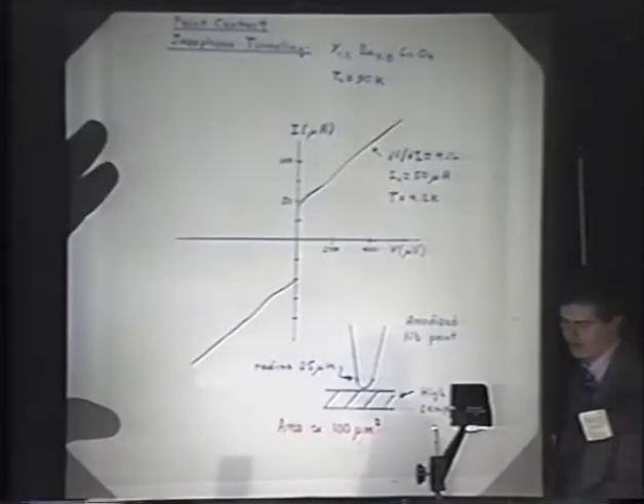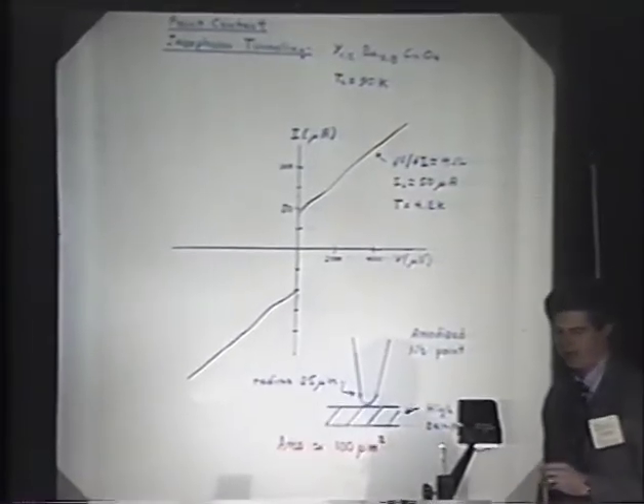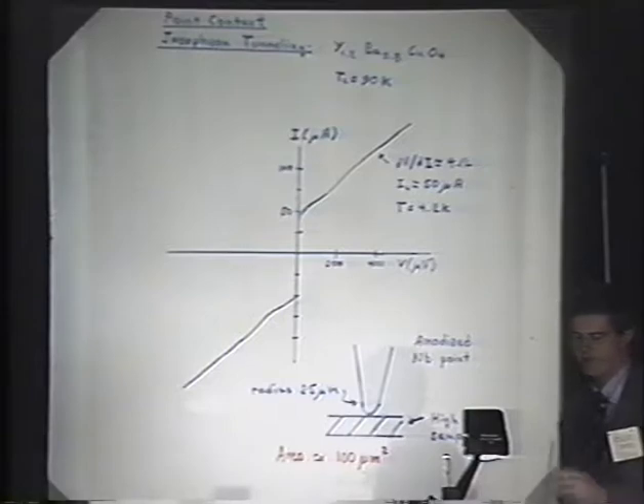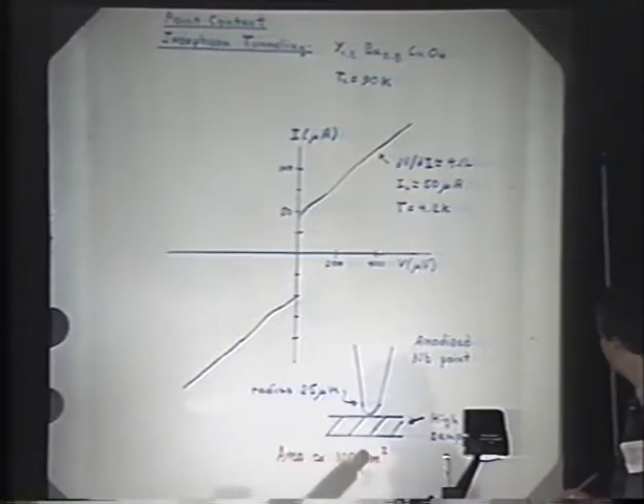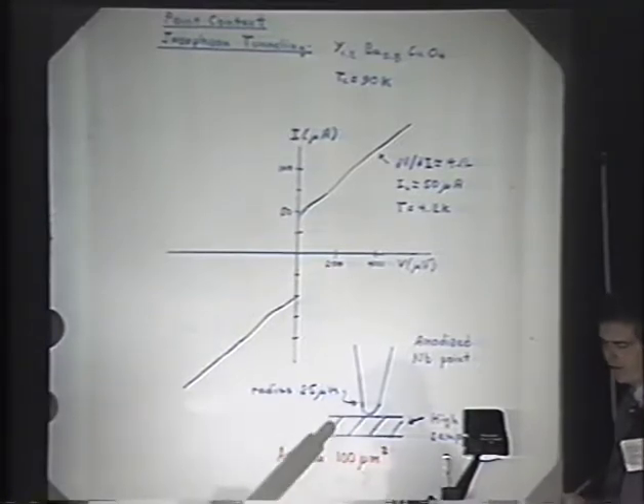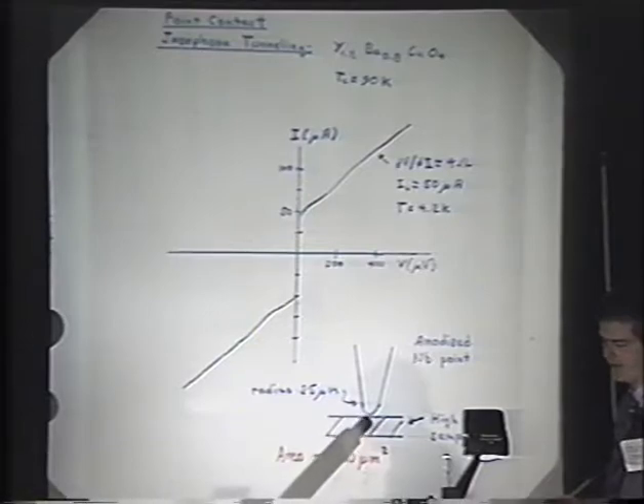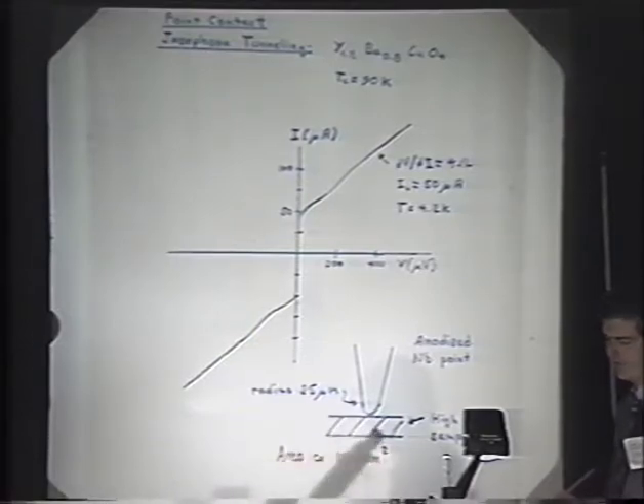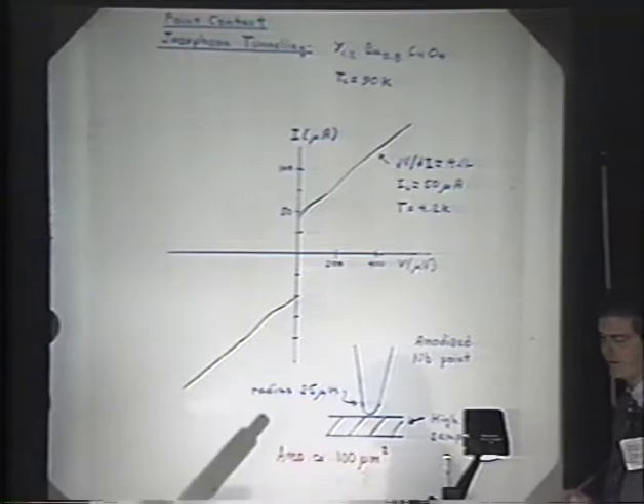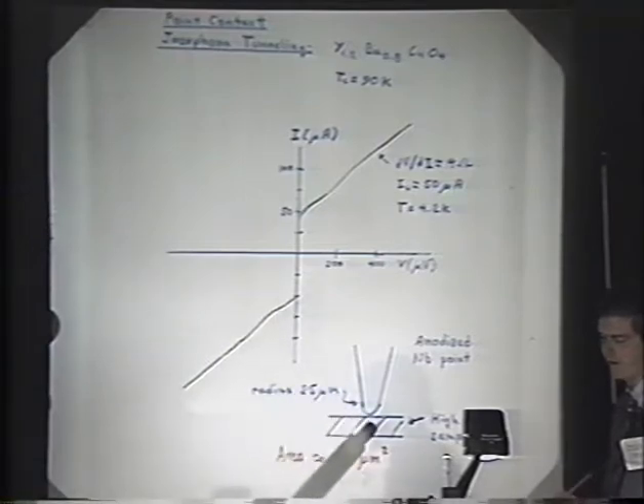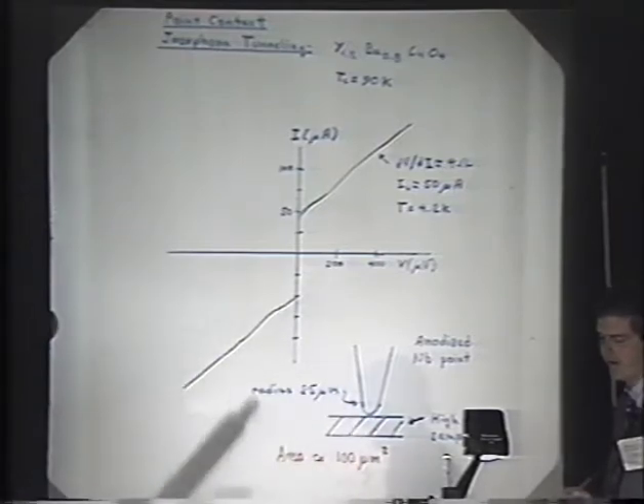Finally, I want to show you a point contact Josephson tunneling experiment. We made a point contact junction, as shown here down in the inset, and we had about a 25 micrometer radius tip, which we could move around over the top of the sample, and then we could vary the pressure of this tip on the flat sample.